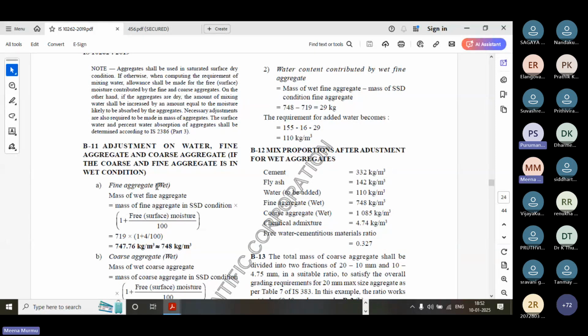Suppose moisture is there, then we have to calculate the fine aggregate in wet condition. What is the wet condition of the fine aggregate? Mass of fine aggregate in SSD condition times 1 plus free surface moisture divided by 100. Earlier it was 719, now it will be 748. So here the weight of the aggregate will be increasing.